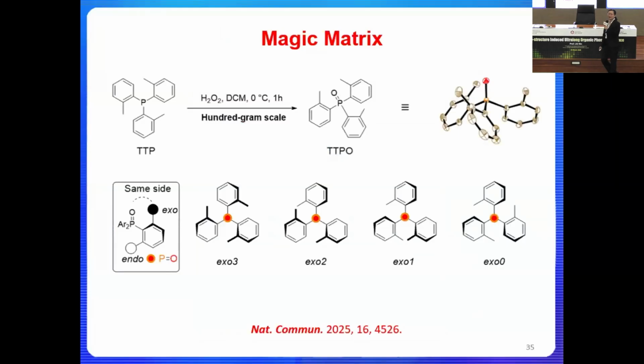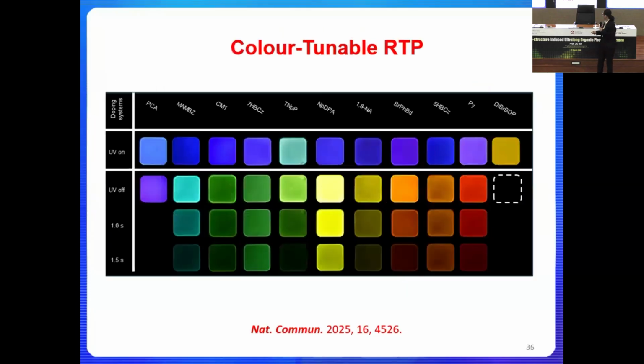Now, this is the molecular structure. It's a very, very simple molecule. But the molecule is specially designed so that it has different conformations, and as a consequence, it cannot be recrystallized very easily. So it will stay in an amorphous state for a long period of time. So that will allow us to process the phosphorescent molecule as we wish. Now, literally, whatever molecule that you have, we will be able to find a good host. And you put your fluorescent molecules into that host. When it is very well dispersed, when the non-radiative decay is pretty much quenched, we will be able to generate the phosphorescent phenomenon for the molecule that you're interested in. We can significantly enhance the lifetime of the emission for the molecule that you're interested in.